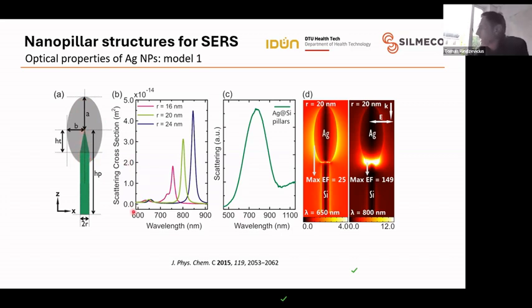And then this turned out to be an important feature to have. The resonance or the enhancement is highly dependent on how wide, for example, this pillar is. So you can tune it across. This is the theoretical simulation, and this is the measurement from a dark field. And what was surprising the most, at least to me, is that the resonance close to the laser that we typically use turned out to be not due to the cap, but due to this enhancement at the neck of the nanopillar. And this is why we thought that we see relatively uniform enhancement over the areas, because when pillars lean towards each other, the necks never really come close to contact. So we don't have these huge variations in intensity. So this was our first attempt to model it.